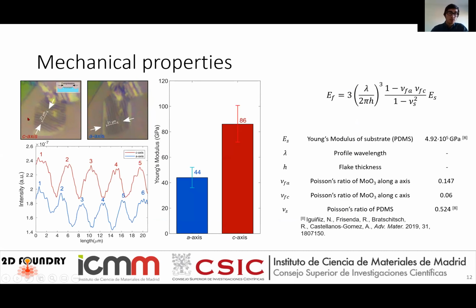Looking at these ripples and measuring them along the 2 axes that we're interested in, you see that the profiles, the wavelength of the profiles along the two directions, are different. In fact, the ripples along the A-axis are the shorter ones. And with this method, we can calculate the Young's modulus with this equation, inserting this value that we have found in the bibliography, and the Poisson's ratio that has been calculated by our theoretical group.